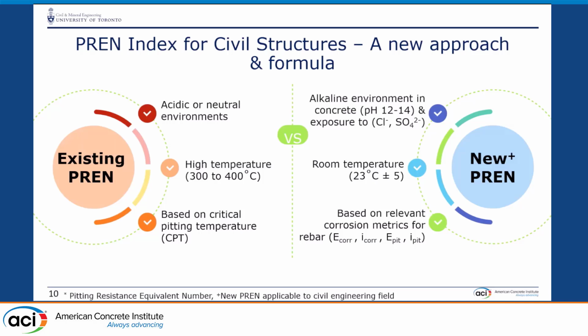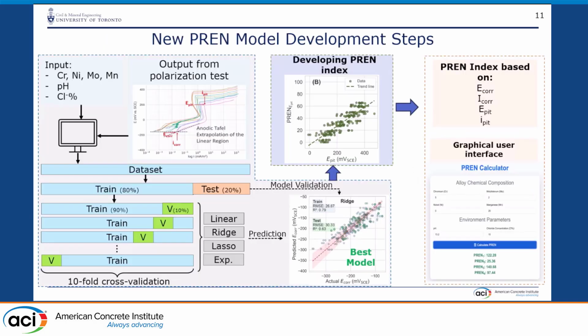I'm not sure how long this work is going to take. And more importantly, exposure to deleterious species such as chloride and sulfate. We're also looking into developing the PREN formula based on parameters that we actually test in the lab. So not critical pitting temperature, but your typical corrosion potentials, corrosion current density, pitting potential and pitting current, as opposed to that. So what we did was a very small test.